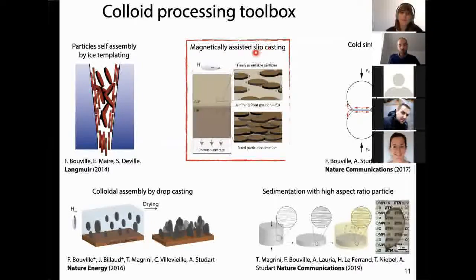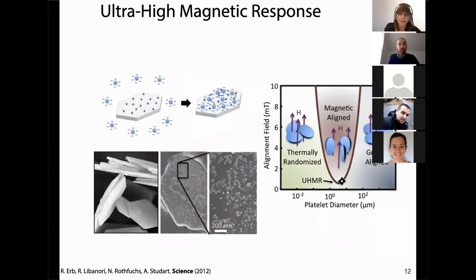And today I'm only going to focus on this one, which is the magnetically assisted slip casting. First, I'll go through a brief description of the process to get this composite, but then I will mainly talk about the mechanical properties. So in terms of process, we're using something that the team at ETH developed a while ago, and the idea is that it uses a very low intensity magnetic field to control the orientation of anisotropic particles. So you start with, for instance, these tiny platelets, and we were lucky enough to find these aluminum oxide platelets, so sapphire platelets, that are 10 micron in diameter and 500 nanometer in thickness, which is roughly the size of nacre. So that was already a good starting building block, let's say.